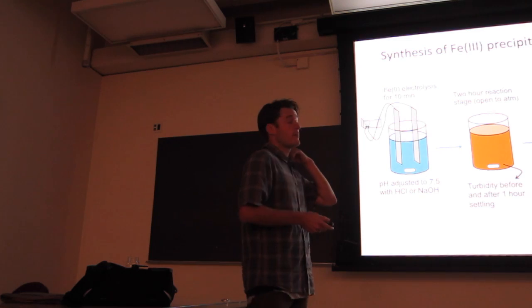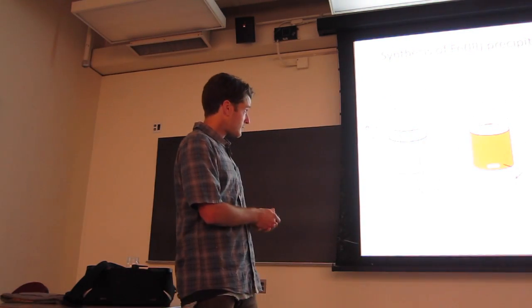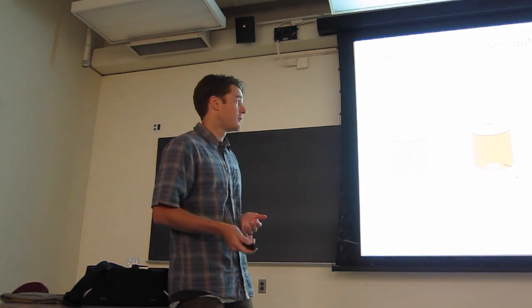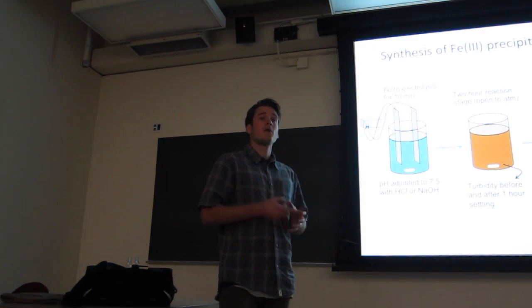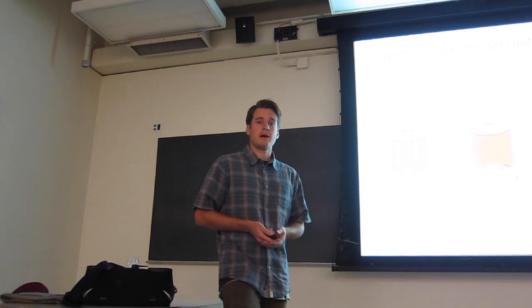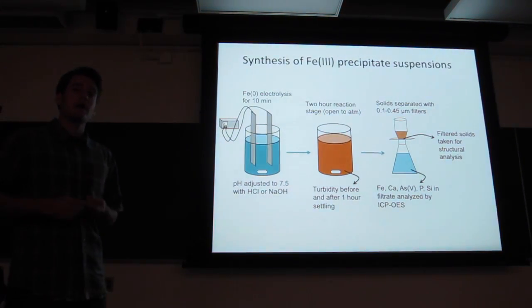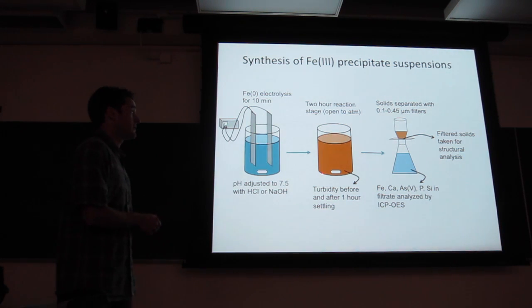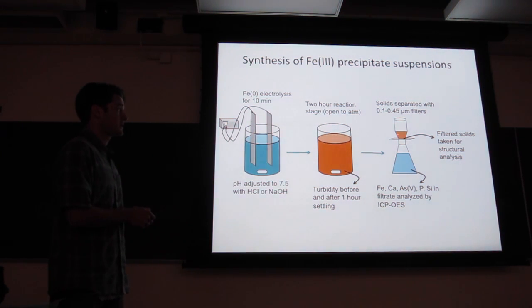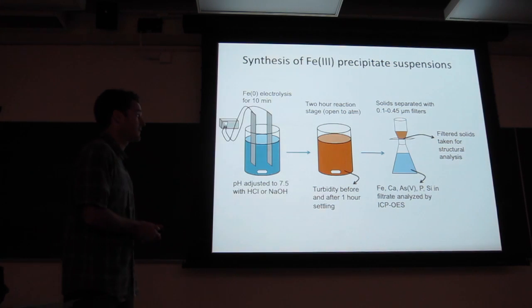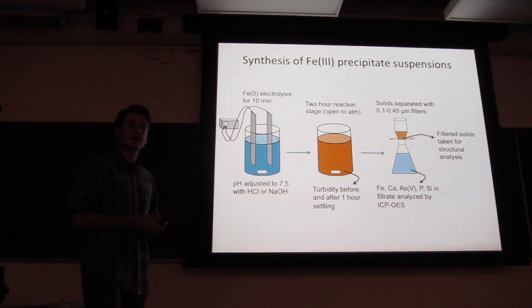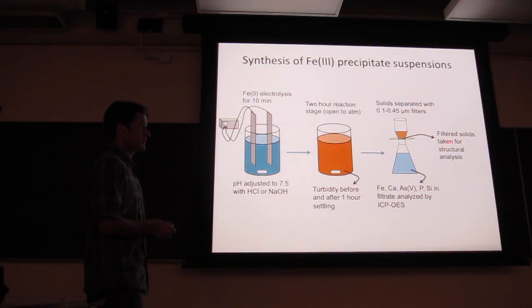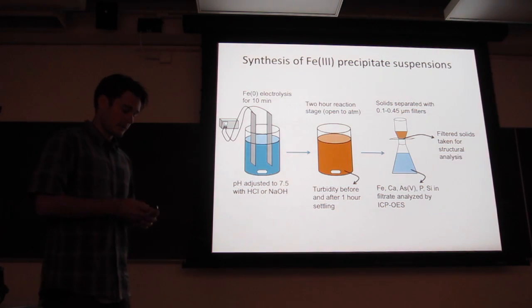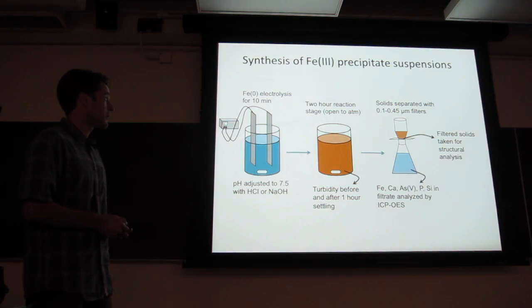Okay, so the typical batch experiments that we run, we apply the current for 10 minutes and generate half a millimole of iron at circumneutral pH, and then we allow all of the reactions to occur for 2 hours open to the atmosphere. And so we take an aliquot of this suspension and measure turbidity before and after 1 hour of settling. And then we filter all of the solids using 0.1 or 0.45 micron filters, and then we measure ion uptake with ICP-OES. Then we take the filtered solids finally for this molecular scale characterization that I'll be talking about later.